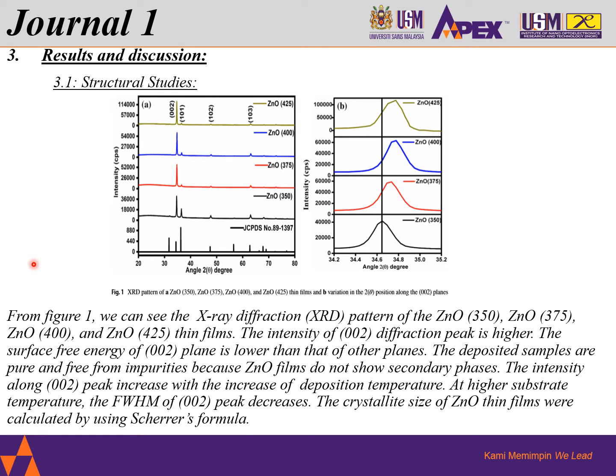The intensity of the 002 diffraction peak is higher. The surface free energy of the 002 plane is lower than that of other planes. The deposited samples are pure and free from impurities because the zinc oxide films do not show secondary phases. We can see from the figure that the zinc oxide films do not show any secondary phases because the deposited samples are very pure.